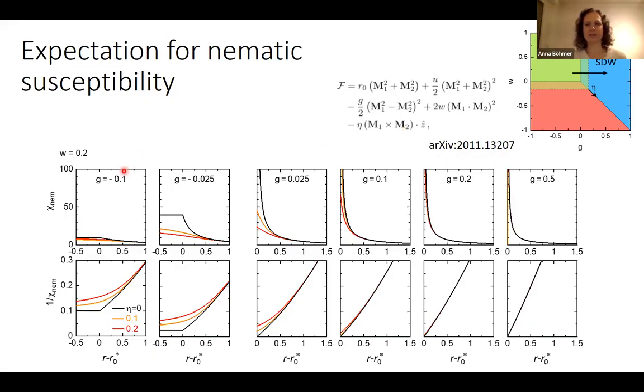So what's plotted here is the calculated nematic susceptibility on a path through that phase diagram as a function of a proxy temperature down to a transition. Here, the transition in 0 eta field. So we see deep in the spin vortex crystal phase, there is a finite nematic susceptibility. It's increasing and then it's cut off at the transition. It doesn't diverge. And once we add a field eta, it gets suppressed and the transition is washed out. If we are deep in the stripe phase, the eta field has basically no effect. In this intermediate one, it suppresses the transition. We go from a divergent nematic susceptibility to a non-divergent one. And the ground state changes from stripe to spin vortex crystal.